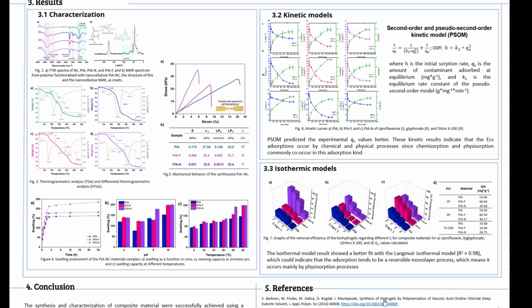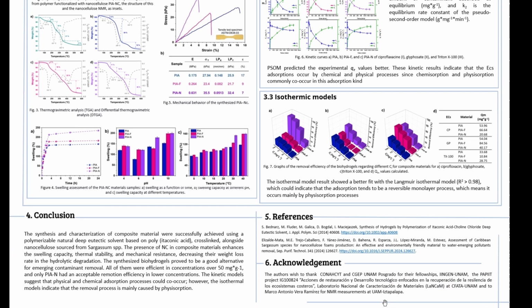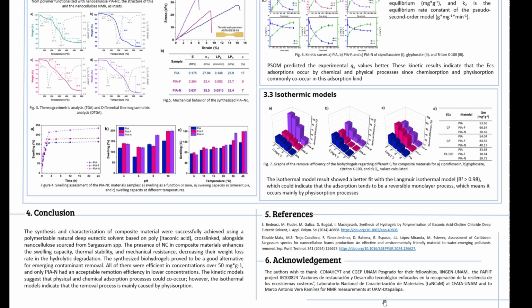Maximum adsorption capacity values indicate that the materials with nanocellulose extracted from one sargassum source have the higher removal capacity for ciprofloxacin and glyphosate. For the case of Triton, the material without nanocellulose expressed the major capacity. The Langmuir parameters suggest that the polymers perform better at higher concentrations than at lower ones. This was supported by the removal efficiency results, which show that it decreases when the concentration is below 100 milligrams per liter. Although having a lower maximum adsorption capacity, the material with nanocellulose from the other sargassum source showed the best removal efficiency for removing ciprofloxacin and glyphosate.